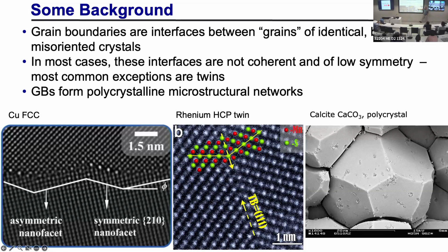And the reason I'm showing you this to complement this picture is what you find out is that most grain boundaries are not flat. There's some curvature to these. And let's say this is a high symmetry plane. If this is a high symmetry plane, all the other ones are generally going to not be high symmetry. And in fact, although we like to study high symmetry interfaces, they are a rarity. Usually they're curved, they're asymmetric. Even if the two orientations of the crystals are symmetric with respect to each other, the boundary plane may be canted or tilted relative to that boundary plane.